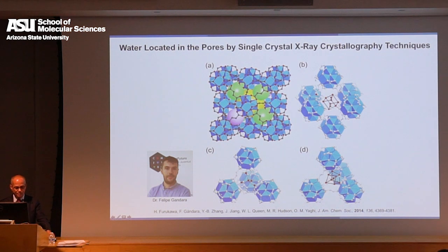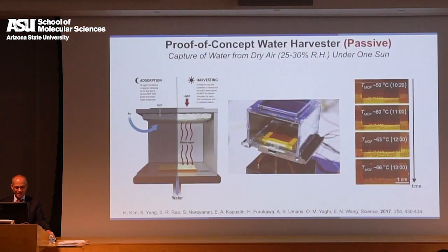It turns out the very first water molecules are bound closely to the metal oxide unit. And so when you're doing the cycling, these, I call them seeds, are not removed. They are stuck to the metal oxide unit through strong hydrogen bonds. But what you're removing are the water molecules that are bound to the seed. So in a way, you have an ice fragment growing inside the MOF at room temperature. And that's what we were cycling: the additional water molecules that are bound to those seeds. Well, that's great, right? Now we have figured it out, and we can do better, right? But before that, we wanted to show that this thing works in the desert.